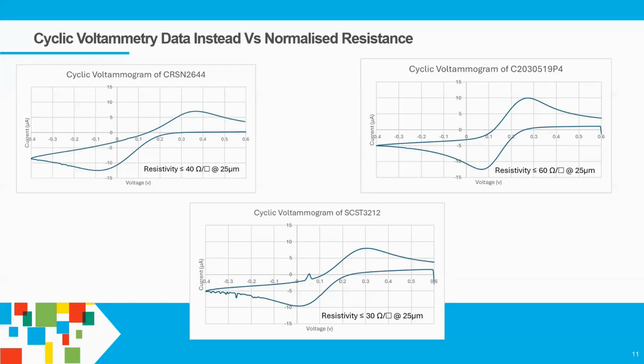And the reason for that is you can make a really conductive paste by chucking in loads of polymer. You cure it, the polymer tightens, you have all those materials coming together, making a lovely conductive track. Electrochemistry isn't going through the material. It's a surface-related phenomenon. So the surface is what's important, not through the material.